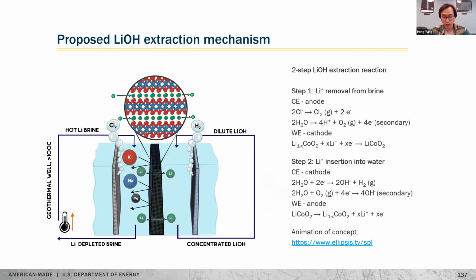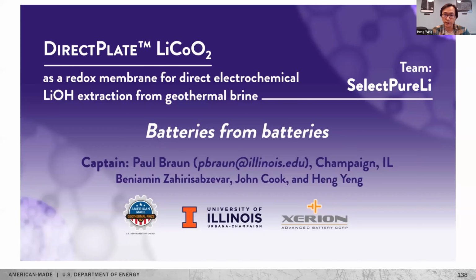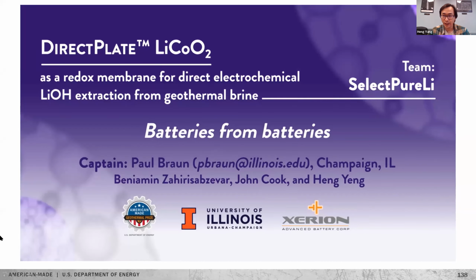In the right-hand side chamber, it started with a dilute lithium hydroxide solution. A reverse current passed through the redox membrane to release lithium. Hydroxide ion formed together with hydrogen evolution reaction, and this process gives us more concentrated lithium hydroxide solution, which we extract after this process. Chlorine gas and hydrogen gas can be collected and form value-added HCl solutions. So we made a video to help demonstrate this concept. Please play and make sure you're unmuted.